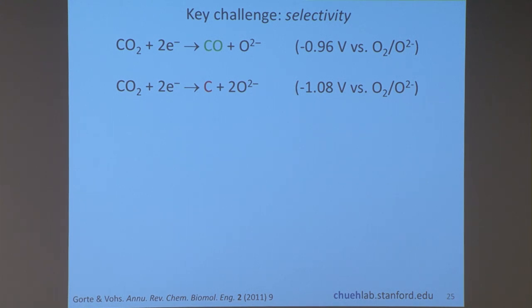So you might ask the question, well, sounds easy. CO2 to CO, just strip an oxygen atom off, you're all set. That's good. But the problem is you can strip either one or two oxygen. If you take one oxygen out, you get CO. If you get two oxygen out, you get carbon. So this is, by the way, great. If you can go to carbon, then you can just sequester it in carbon.